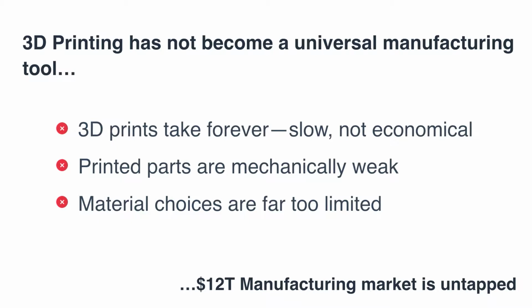This is not so much a problem for the metals, but on the plastic side, polymers derive all their strength from chain entanglements. They have memories of their prior form. So if you're laying down a material layer by layer, you're going to have poor interfacial adhesion between those layers. Or if you're sintering particles together, you're going to have poor interfacial adhesion between those particles. And that was something that is a big problem with additive as well.